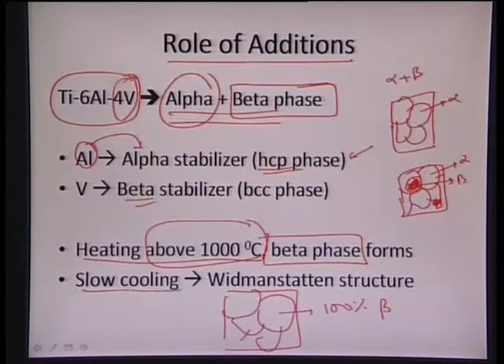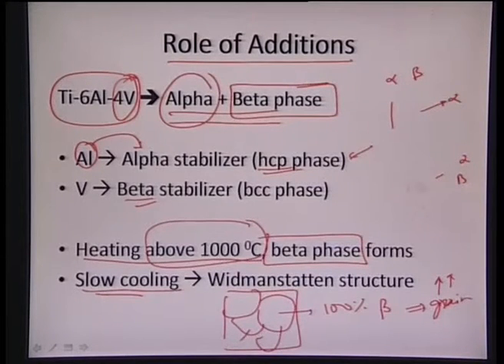and once we start cooling it very slowly, then what will happen, that the material is basically being retained at very high temperature for very long time, and it cools down very slowly. So there is much more increase in the grain size. So that is a problem with the slower cooling, that we tend to see something called Widmanstatten structure. So in the Widmanstatten structure, we basically have a structure like this.